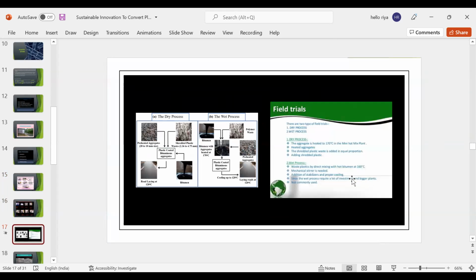Okay, so there are two basic processes or field trials we can say. First is the dry process. So what happens in the dry process? The aggregate gets heated at 170 degrees Celsius in a mini hot mix plant. Then the shredded plastic, in equal proportion, gets mixed with the bitumen, and then it is used for the road. While in the wet process, the waste plastic directly gets mixed with the hot bitumen at 160 degrees Celsius, and then mechanical stirring takes place. Then some stabilizer gets added and proper cooling is required. So basically the wet process takes more time and requires a lot of investment and bigger plants. That is why the wet process is not commonly used and the dry process is most useful.